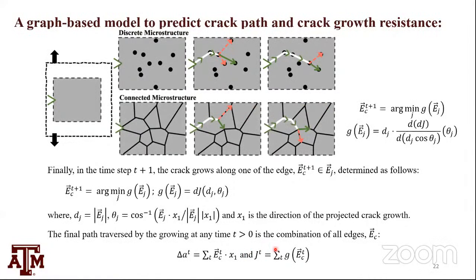I can do the same for this connected microstructure. The challenge here is that this stays the same, but my G slightly changes. The equation may seem complicated, but this G definition is actually easier. dj is no more a function of the distance d. The distance is outside, and my increment per unit projected crack length is a function of the inclination alone. So a little bit more complicated, a little bit simple.